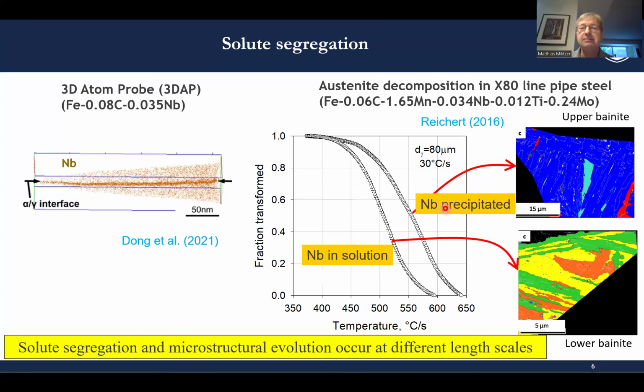What we see here is the fraction transformed as a function of temperature for a cooling rate of 30 degrees per second. You see a shift in transformation temperatures of about 50 degrees when niobium is in solution, so it affects the migration rate of these alpha-gamma interfaces. And the transformation products are very different. For the higher transformation temperature, we see something that we call upper bainite with a low density of high-angle boundaries, versus when we reduce the transformation temperature, we get what we typically call lower bainite with a high density of high-angle boundaries. That's actually the preferred structure for the coarse-grained heat-affected zone in these steels.